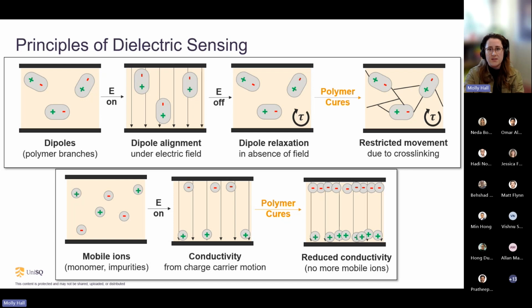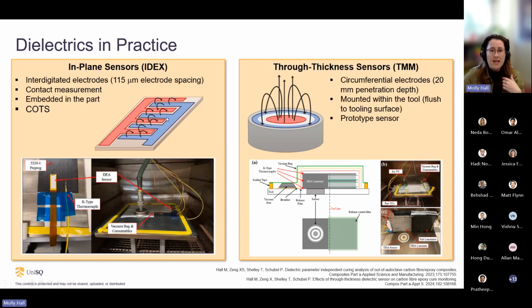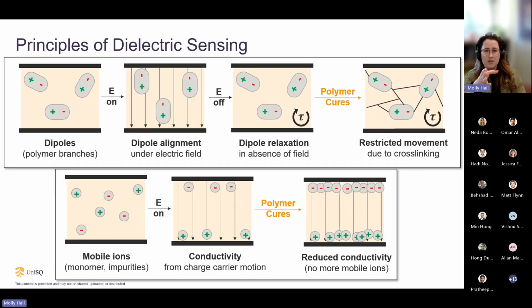What happens with this sensor? So you have two electrodes. In the previous slide, you see in the interdigitated, they're comb electrodes that are spaced in between each other. In the TMM sensor, we have the circumferential electrodes. What I'm showing here, just for the visual, is actually a parallel plate configuration. So you have one electrode on top, one electrode on the bottom, with your material under test in the middle. And this is not what I used. It's just a common way of representing how they work.